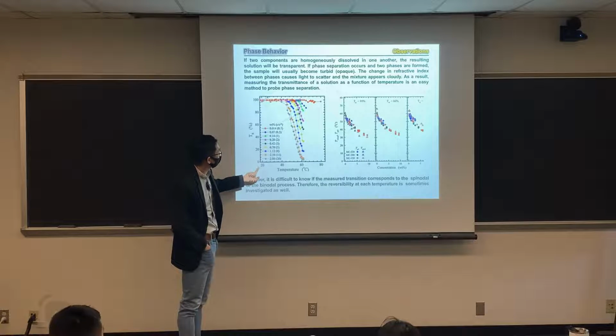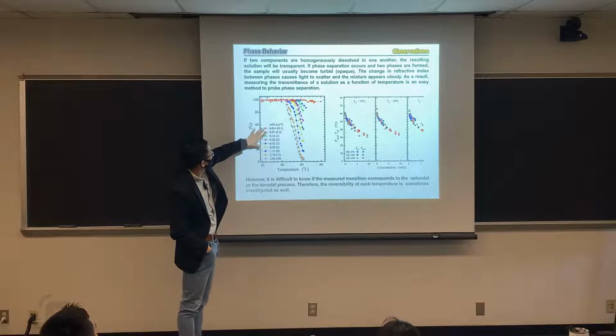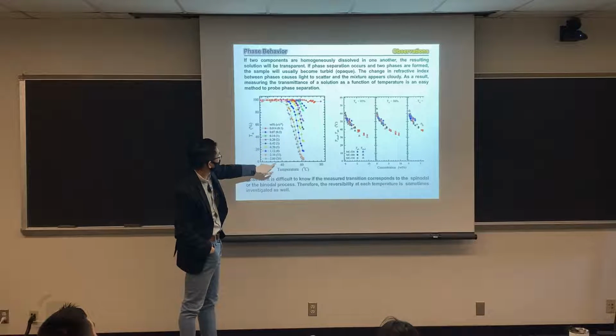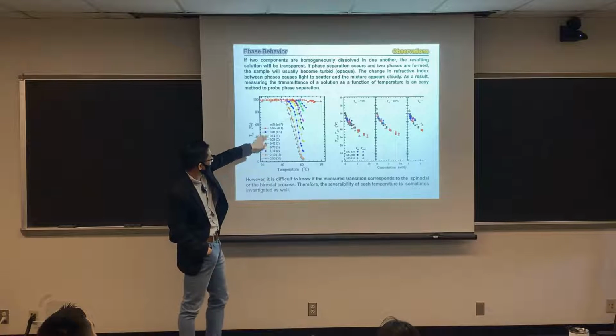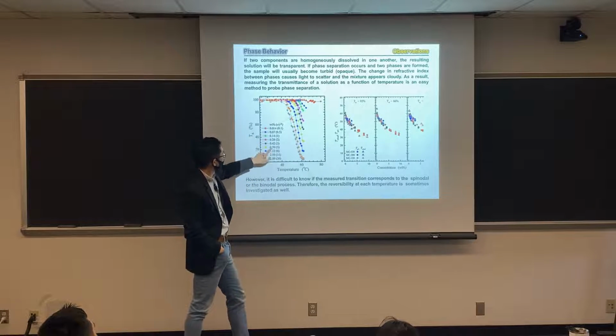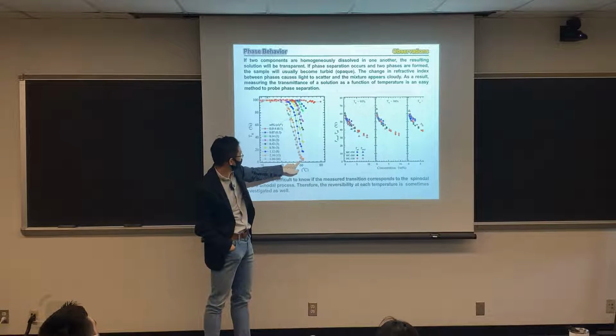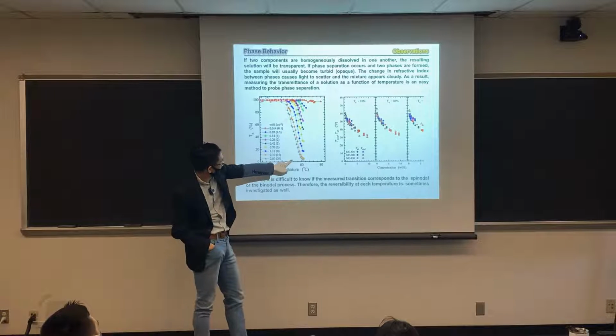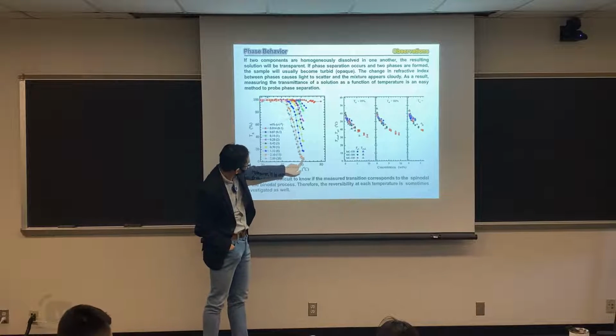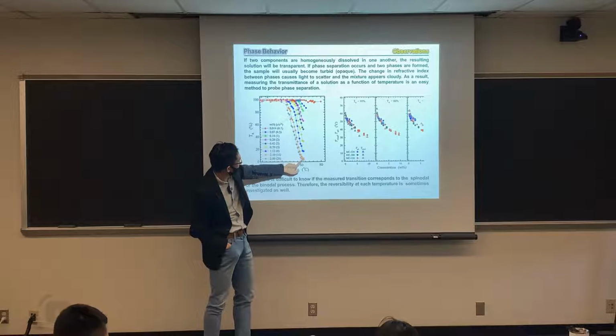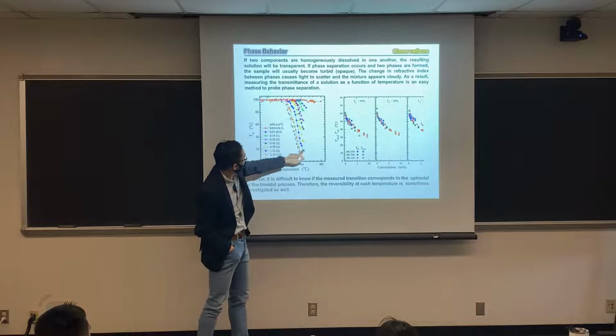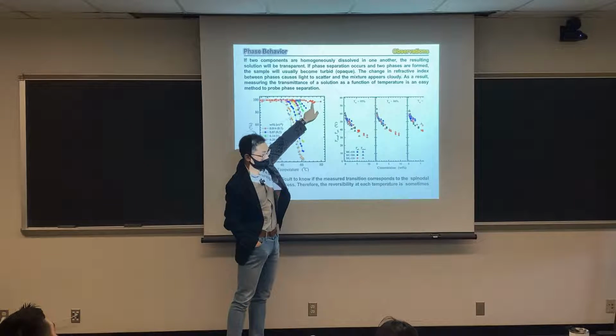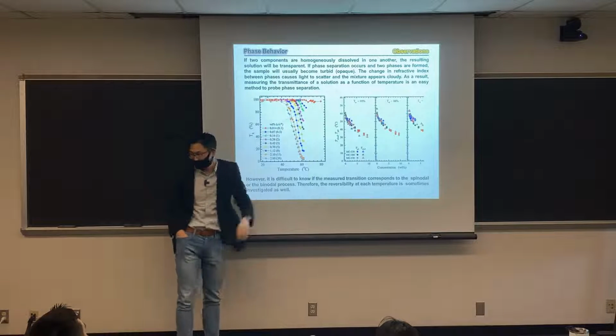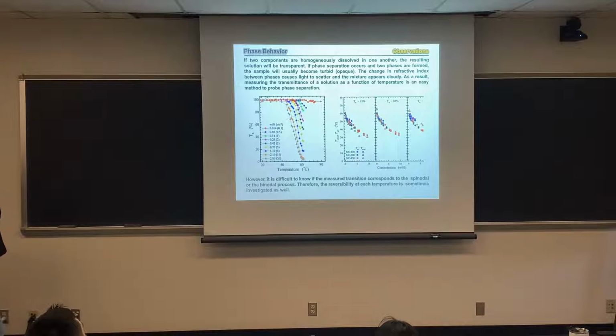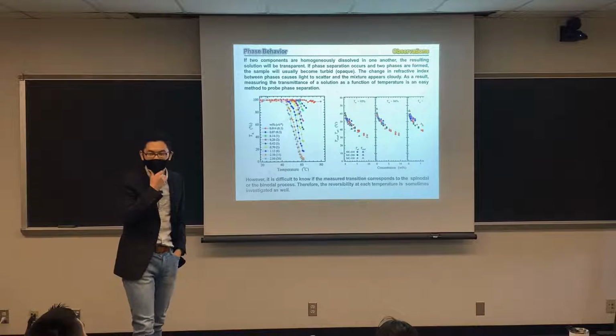Here is an example showing that if we mix two materials at different concentrations, when we go through this particular temperature, we can get the phase behavior. You can assume when transmission is low, that means it's phase separated. You can see when you load more polymers in terms of concentration, this goes up, but the critical phase separation temperature goes inversely, okay? If you put in just a little bit of polymer, even at high temperature, it will be stable. So this basically is a UCST or LCST behavior, everybody?